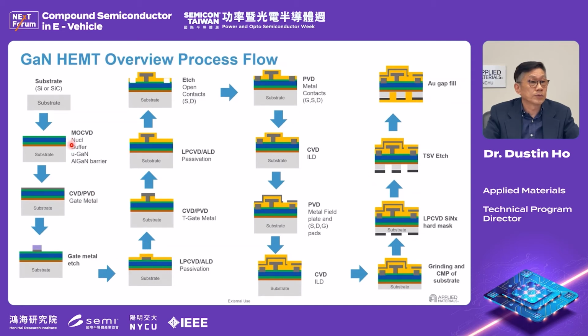The main difference will be the T-gate. So start with the MOCVD with the buffer layer into the etch, and then you have the passivation. You need another etch so you can form the T-gate, and then another passivation, ALD and LPCVD passivation isolation. Then the etch for the source and drain contact.